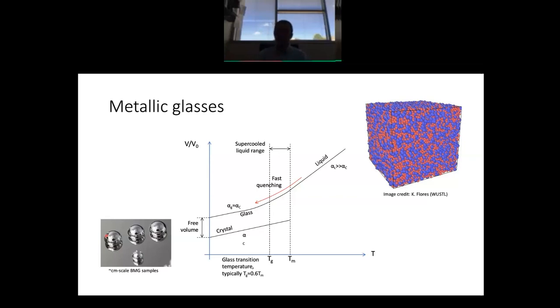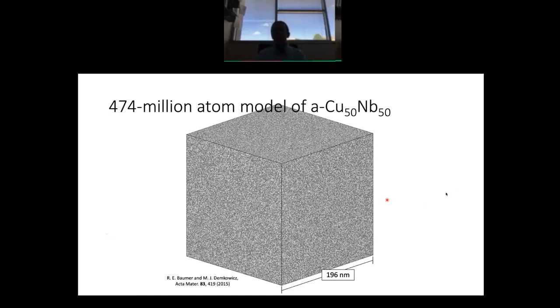That's a topic that I addressed with one of my former students, Richard Baumer. He actually went to Livermore and spent a summer working with Vasily Bulatov. This is where that sort of grand challenge allocation occurred. He studied collision cascades in a model of amorphous copper niobium, 50-50 amorphous copper niobium. This particular model had almost 500 million atoms in it, and it was about 200 nanometers on the side, on the corner. Okay, this is by far the largest atomistic simulation that I've ever done in my group. Okay, so this is a view of what that model looked like.